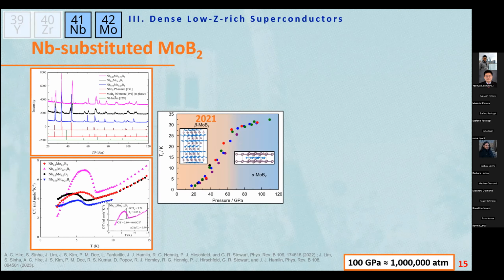So indeed, we found that the niobium substitution stabilized the MgB2 structure in molybdenum diboride. We did 10%, 25%, 50%, 75% substitution of niobium into the molybdenum diboride, and in all of them we found the MgB2-like structure at ambient pressure. And not only did we stabilize the MgB2-like structure in the molybdenum diboride, but we also have superconductivity at ambient pressure, around 8 Kelvin. When you substitute niobium in the molybdenum diboride, without pressure, you will have superconductivity.